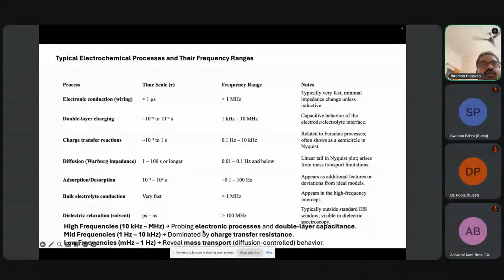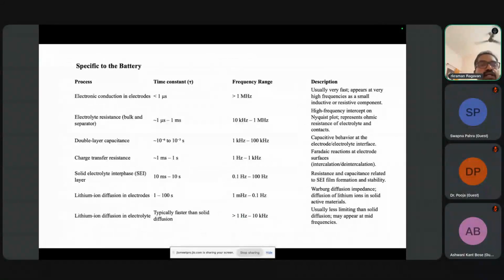Okay. So now let's stick to the battery. You can see the electronic conduction in the range, as I said, above 1 megahertz, and the electrolyte resistance, that is the separator that you have. They will respond in the microsecond to millisecond region, that means in the kilohertz to megahertz region, and the double layer, as I said, in the kilohertz to 100 kilohertz region. And the charge transfer reaction, like cobalt switching its oxidation state in the case of a lithium-ion battery, which I discussed, will happen in the hertz to kilohertz region. And if you have a solid electrolyte interface, the resistance due to the solid electrolyte interface you would see anywhere between 0.1 hertz to 100 hertz.